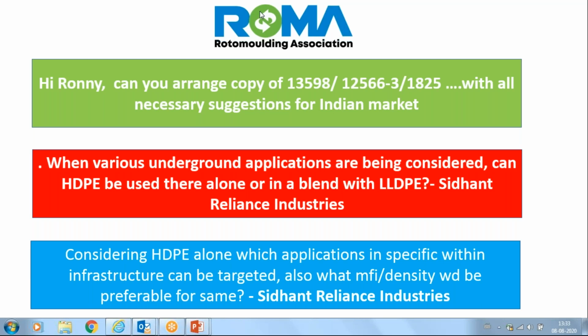If you make a blend, normally if you blend LLDPE and HDPE, let's say a pipe HDPE and a film LLDPE, you can get a kind of super linear, which is a fantastic material for rotomoulding if you have the correct molecular weight distribution. But for rotomoulding material, you should not dry blend it. You should never ever dry blend any materials. You should use them alone. So I would say for all the underground applications, big and small, it doesn't matter, use around 940, let's say 938 to 945, ideal materials.